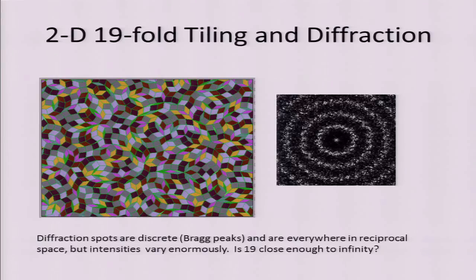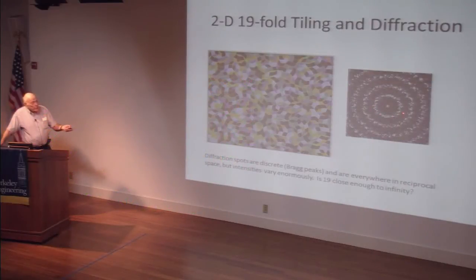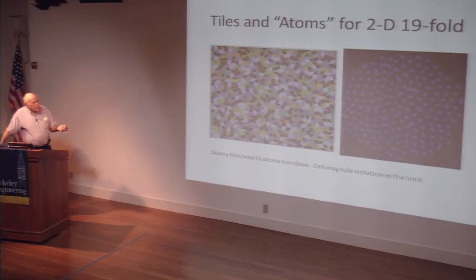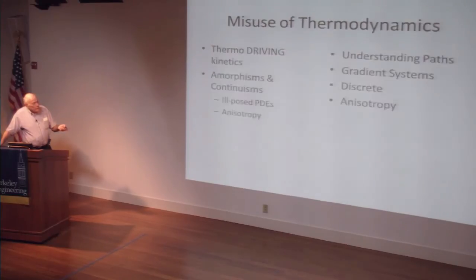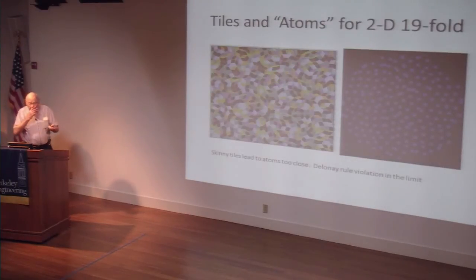Now, to me, that looks like a glassy diffraction pattern, except each of these are Bragg peaks. So if I had gone to more than 19, and this is what the tiling looks like, and here is the tiling again, and this is what the atoms might look like. So it is possible to create something isotropic that's highly structured. And it's structured in this case in the same way as quasi-crystals are, except now instead of being just icosahedral symmetry, it has all the symmetry. And so we may be on the verge of another kind of structure that is like quasi-crystalline, but it is isotropic, and it has different stability.